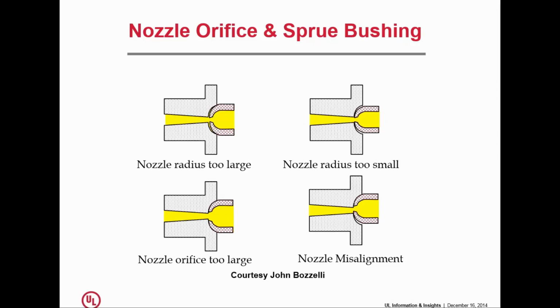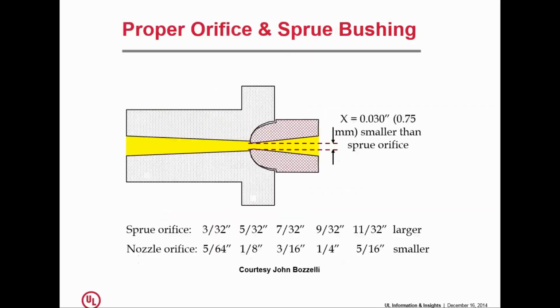But first, take care of the fundamentals. And make sure that you take full advantage of the opening in the mold. The sprue bushing has a certain O dimension. The nozzle tip should be matched as closely as possible to that sprue bushing. Now, I know this sounds like very, very basic stuff, but I cannot tell you the number of times, not only in my own plant when I worked in a plant, but also now when I go into other plants, where you see a nice big 9/32 opening on the mold, and you see a 1/8 inch nozzle tip on there. And it's like, why? Why are they doing that when it could be a 1/4 inch tip?